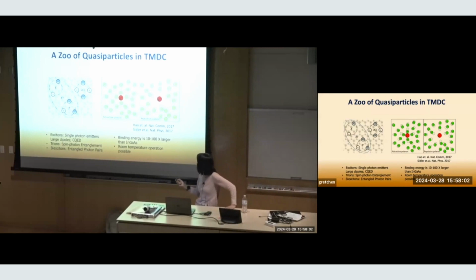All of these particles have binding energies about 10 to 100 times larger than in traditional semiconductor quantum wells and quantum dots. That makes these quasi-particles very important to study for all sorts of optoelectronic devices. In the realm of quantum information science, these particles have different roles. For example, if you can isolate a single exciton, it will emit photons one at a time, so it becomes a solid state single photon emitter. A single trion serves as a way to entangle spin and photon in the material. And a biexciton becomes a source of entangled photon pair generation.